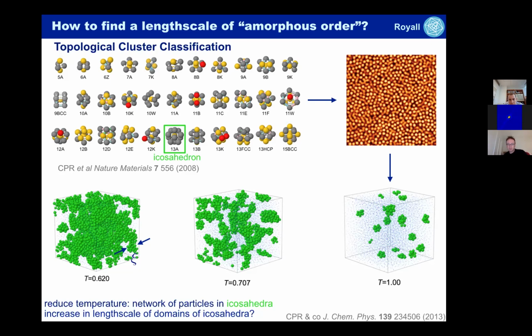But in these confocal microscopy data, what we have is an increase in the number of icosahedra as we reduce the temperature. So in this system, temperature equals 1 is a liquid, temperature equals 0.62 is what we call a supercooled liquid whose viscosity is 10,000 times higher than the normal liquid. The relaxation time is 10,000 times slower. And what we see is there is an increase in the number of icosahedra.